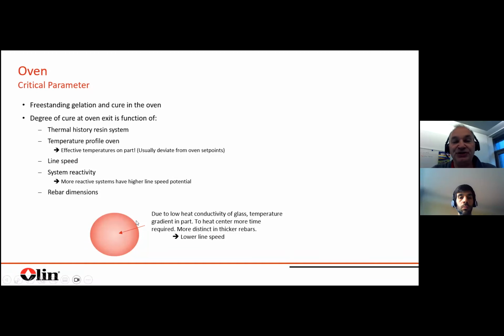You have this feature of glass fiber that the heat conductivity of glass is not so good. So that means it takes some time to heat the center of your profile. And this is something which is hard to overcome. So you need some more time, so it will slow down the process. And this is something really to consider.